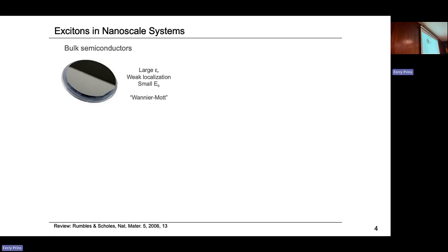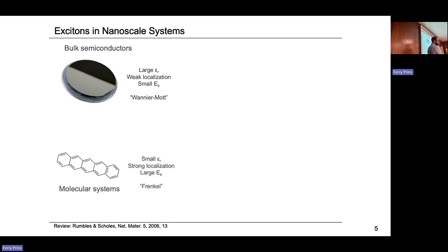On the other extreme, this is pretty slow here. On the other extreme we have molecules, which if you're a physicist you would call a semiconductor, and if you're a chemist it's a molecule. At the end of the day it is just two extremes of the same spectrum, where now we have a small epsilon, so the excitation is going to be very localized—localized on the molecule in most cases—which leaves us with a very large exciton binding energy. If we photoexcite this molecule, you're going to create what we would refer to as an exciton.